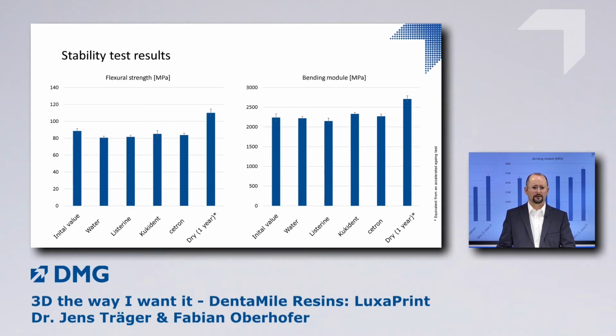And what we see here, both for the flexural strength as well as for the modulus, is that over 1,000 cycles there's no degradation in mechanical properties. And on the right-hand side bar, we see an accelerated aging test standing for 1 year of time. And we also see that there's no degradation in mechanical values over time. In fact, in this experiment, the flexural strength even is higher after 1 year than the initial value.